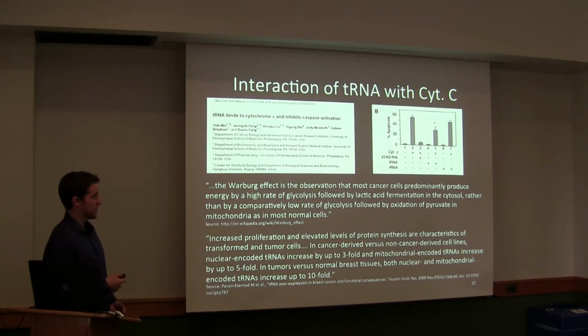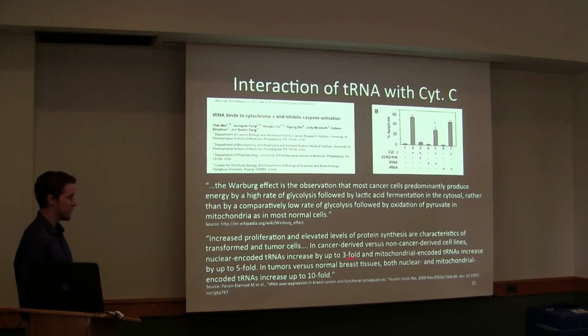It's also very interesting that there is this interaction because of the Warburg effect, which is where cancer cells predominantly produce energy not through aerobic respiration, but by glycolysis, which is an anaerobic method of producing energy. And why that's interesting is because in cancer and tumor cells, there can be up to a 3 to 10-fold increase in the amount of tRNA in these cells. And so if you have this drastic increase in tRNA due to the increase in protein synthesis in these cancer cells, it could potentially be related to tRNA basically impeding the ability of cytochrome C to participate in aerobic cell respiration. So this could potentially be one explanation for the Warburg effect in cancer cells.